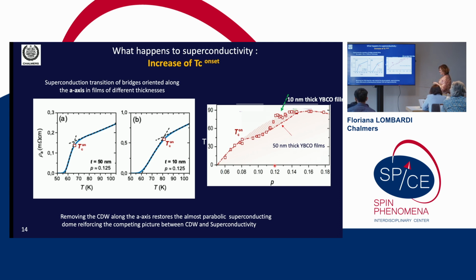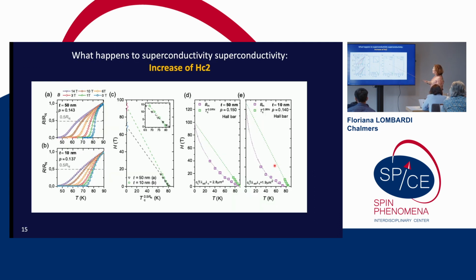Okay, so this is the TC. And what happens to the HC2? Well, something interesting happens also to HC2. These are the resistive transitions for the 50 nanometer film, and this is for the 10 nanometer film as a function of magnetic field. And then you can retrieve the temperature dependence of HC2 by considering for every field the temperature at which the resistance is one half of the normal state. This we did in our standard PPMS up to 15 Tesla. But nevertheless here you do see that the slopes are completely different for 10 nanometers and 50 nanometers.